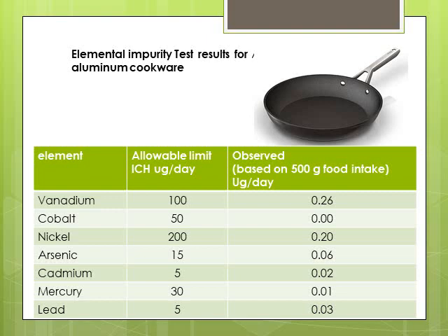So for vanadium, we could have 100 microgram per day. Cobalt is 50, nickel is 200, arsenic is 15, cadmium is 5, mercury is 30, and lead is 5. Now the amount observed in the water sample collected with this pot are the column to the right. So for vanadium, we see 0.26 microgram per day, given that if we eat